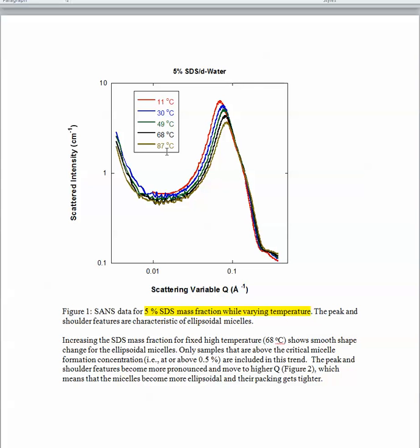When we heat up, the SANS intensity goes to higher Q. So you see the main peak, the structure factor peak. You see a drop off as 1/Q^4, that's the form factor, for the exponent of -4. There's a shoulder here, which tells us that these are not spherical, but have two sides, it's ellipsoid.